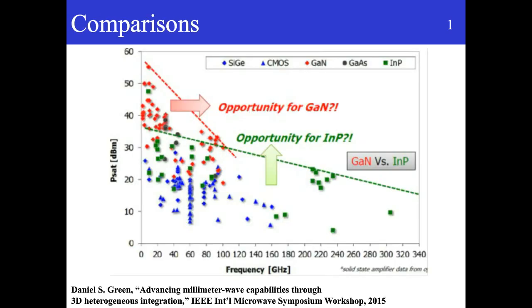This graph here, borrowed from Dan Green, shows the saturated power versus frequency that people were able to obtain. The green dots represent indium phosphide, the red ones represent gallium nitride, and then you also have the gallium arsenide as the black circles. You can see that the very high frequency is dominated by indium phosphide, and then the very high power but lower frequency is dominated by gallium nitride. This chart doesn't show the cost, but typically gallium nitride and indium phosphide are more expensive.